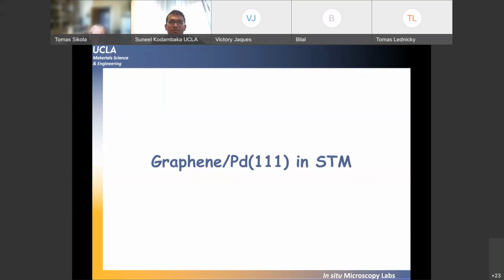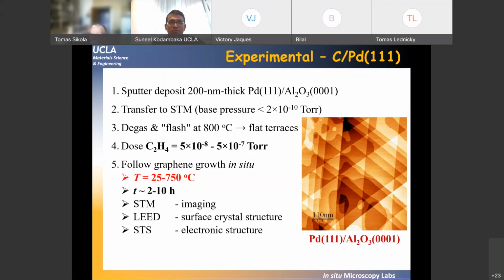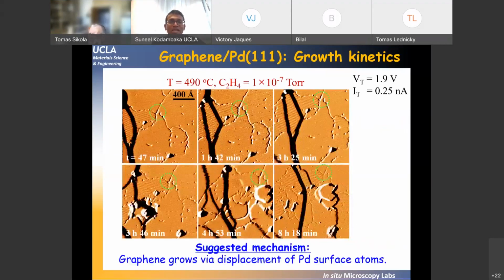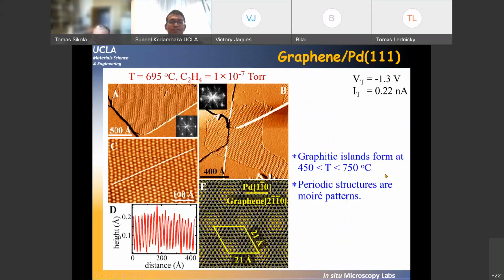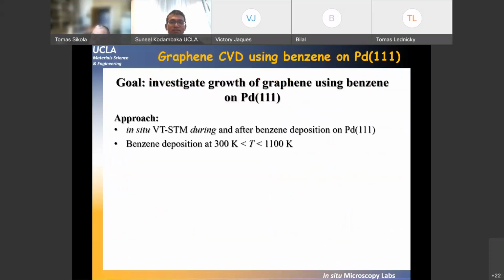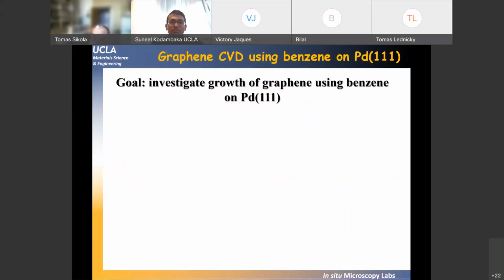So we've done similar experiments with the graphene growth on palladium. I will not go through any details. I just want to show you that we can do this and anybody can do this. This is a palladium surface that's exposed to ethylene, and eventually you get graphene. This experiment was done for 8 hours, but you don't need to do it if you increase the pressure. And you can quantify the behavior of how graphene grows.